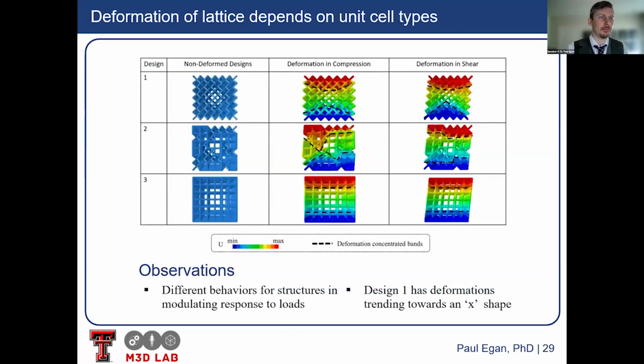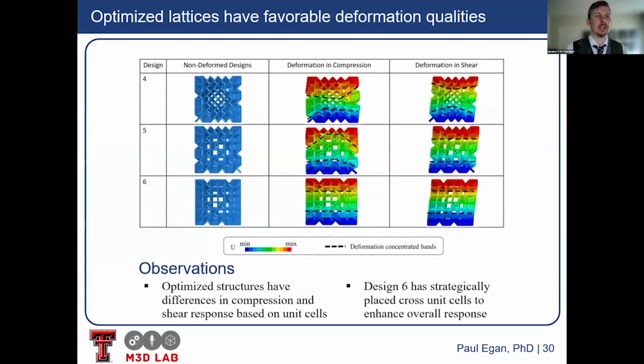And so just briefly, if you look at the non-optimized designs, particularly this middle one that's more randomly put together than the homogeneous ones, it doesn't really have a directed mechanical response that's consistent across it in compression or shear. But whenever we optimize them, you can start seeing a more directed response here where it's more ordered and optimized for how you're distributing the stress through the system and how it's deforming under those loads.